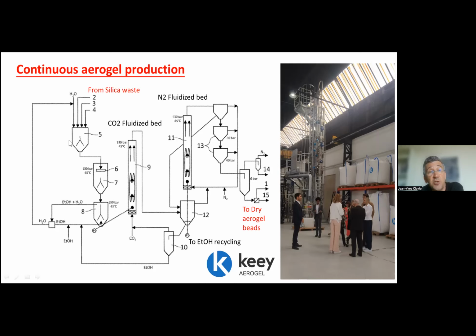A gel formation using a process in high pressure, high temperature water. Then we make the beads under pressure. Then we exchange the solvent with ethanol. Then we dry the solvent with CO2, and then we depressurize and we exchange the solvent CO2 with nitrogen in a second fluidized bed column.